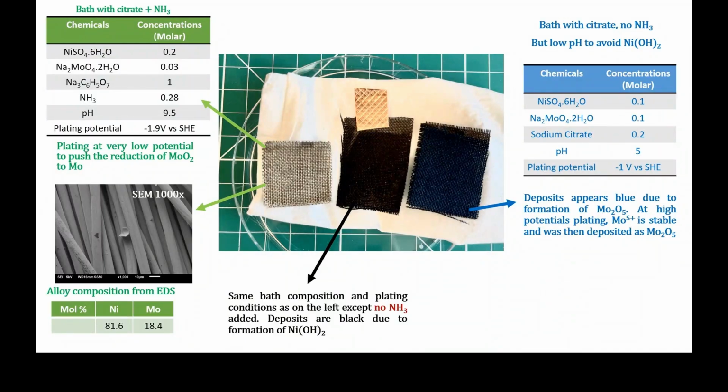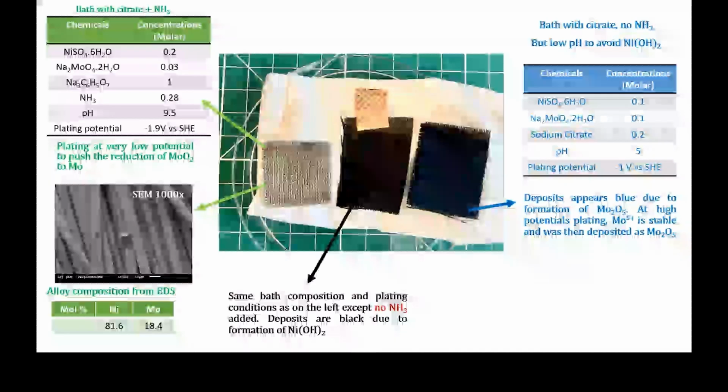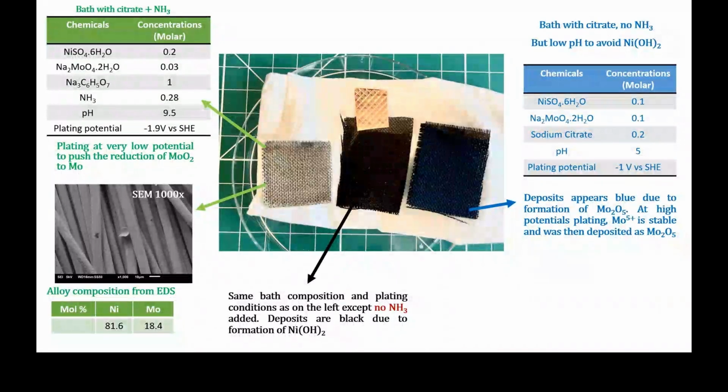These fibers that are shown in the SEM image are carbon cloth, being coated, and the table below shows the molar ratio of nickel to molybdenum. So it's that kind of information from which we calculate the individual charge yields of nickel reduction and molybdenum reduction, and we have to make a guess whether molybdenum underwent a 2-electron reduction or a 6-electron reduction. So jury's still out, I think.